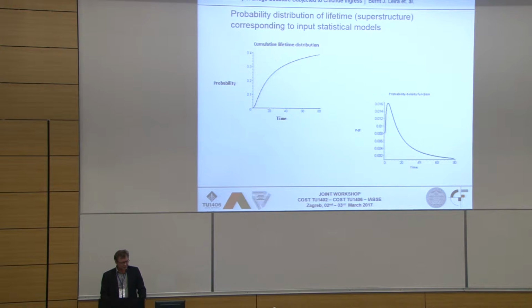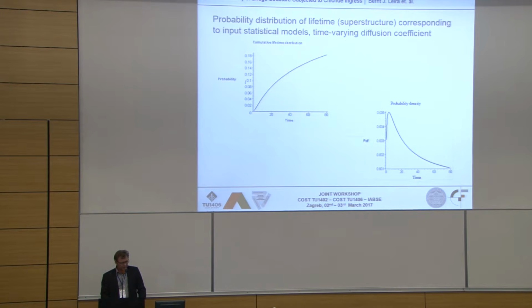Now this is again with a constant diffusion coefficient. So here we have 0.4 after 80 years, but also the peak is located at pretty much the same spot, around 6 years. But we also see that now the upper tail is faster decaying, because the time-dependent diffusion in the previous figure means that the diffusion coefficient is slowing down. It becomes lower with time due to blocking in the concrete. So this is now an exponent of 0.4, roughly the inverse square root of time.